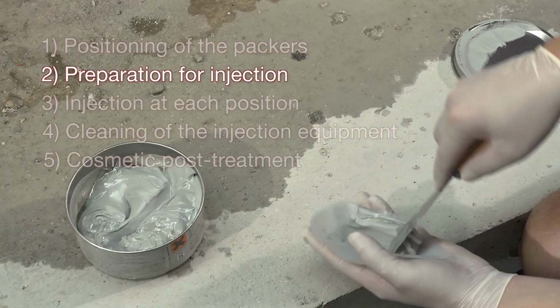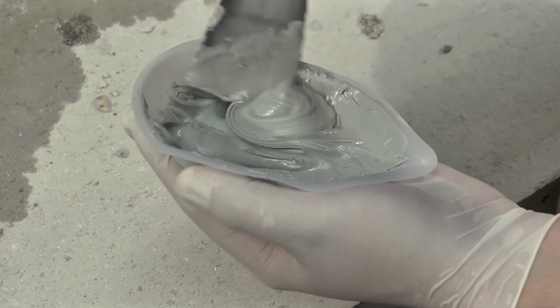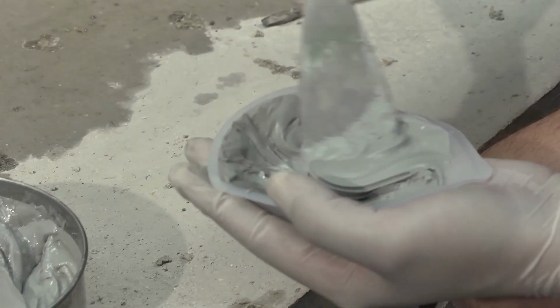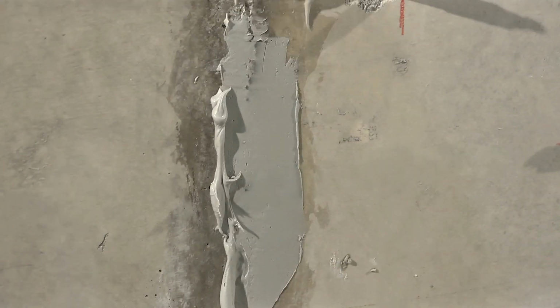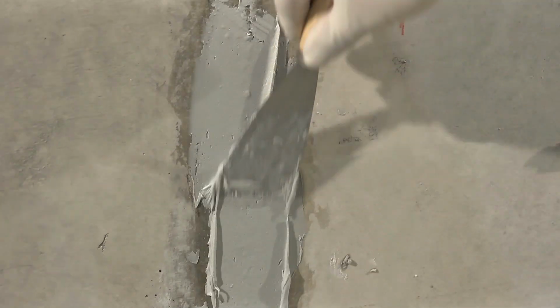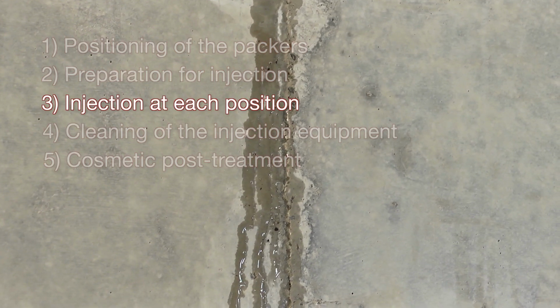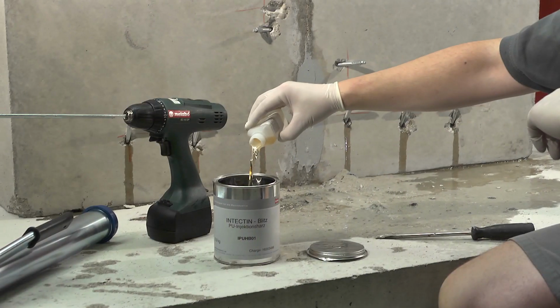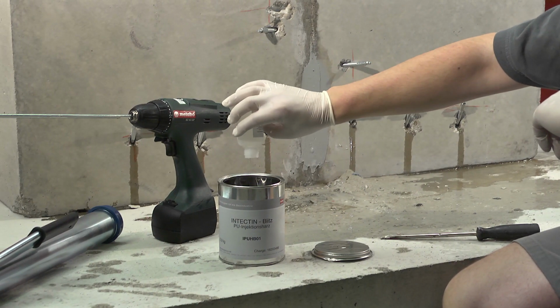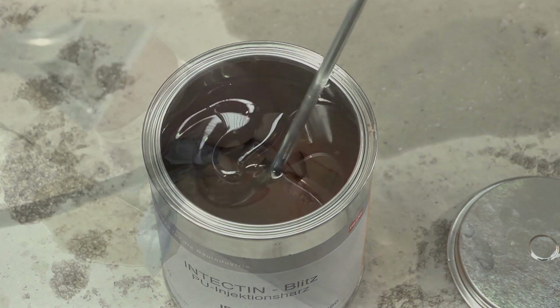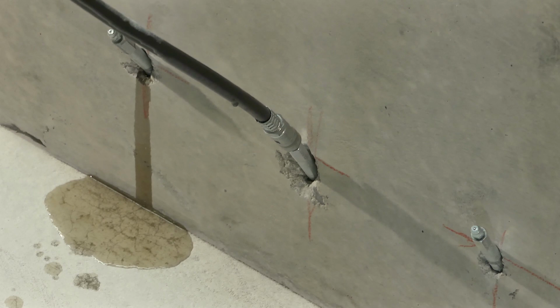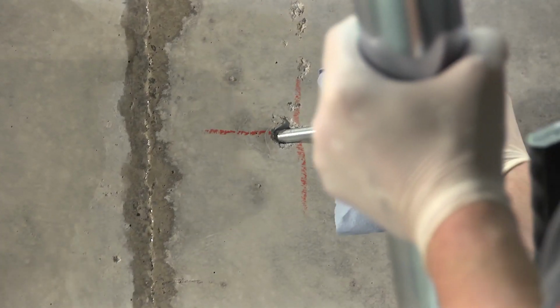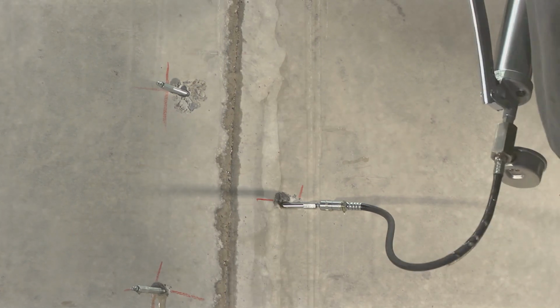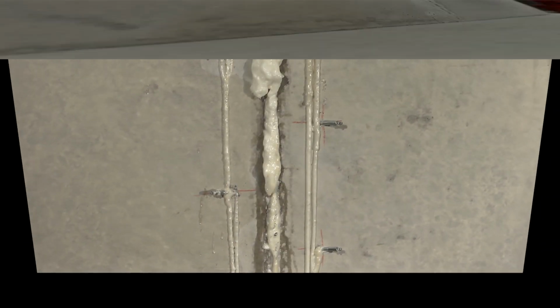For phase 2, flank sealing compound can be used to avoid accidental seepage of resin during injection. No injection should take place until the filler compound has fully cured. For phase 3, pre-grouting is only required for actively leaking cracks or joints. After thorough mixing, Intectant Blitz is injected several times, horizontally in a row or vertically from the bottom to the top, until the flow of water is stopped. Intectant Plus has to be injected before the Intectant Blitz has time to cure.